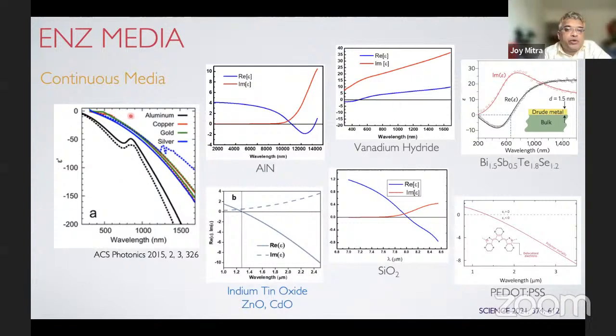Now, obviously, the most famous example would be all standard metals, where the relative permittivity goes to zero at the plasma frequency if you continue from the Drude model, and you have ultraviolet transparency at wavelengths below that, or frequencies above that. But here you can see there is a whole range of nitrides, hydrides, oxides, and topological insulators, and even polymers, PEDOT:PSS, which have recently been shown to have epsilon near zero properties, where the epsilon goes to zero at a particular wavelength.